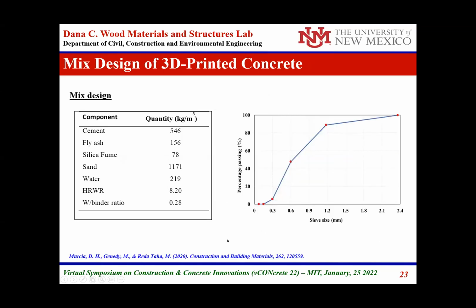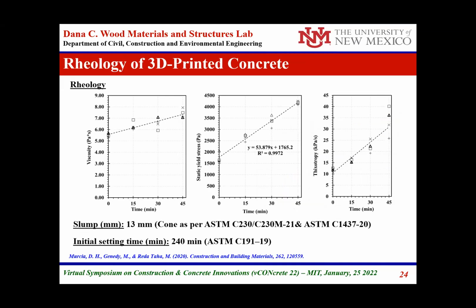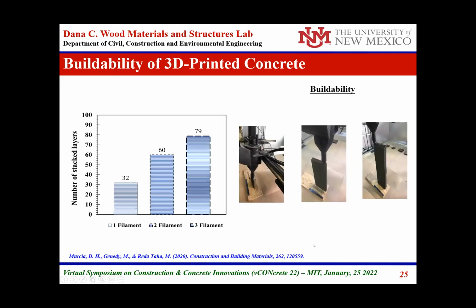We did some testing on 3D printed concrete, a standard mix of concrete, to achieve the requirements for the rheology. We assessed the rheology of the concrete using typical rheometers, and we measured the viscosity, the static yield stress, and the thixotropy of the material. We also measured the slump and the setting time.